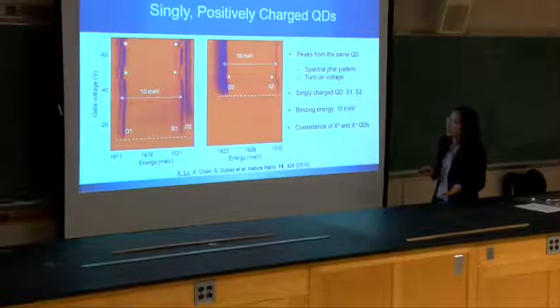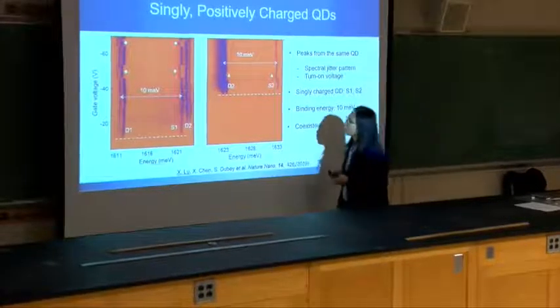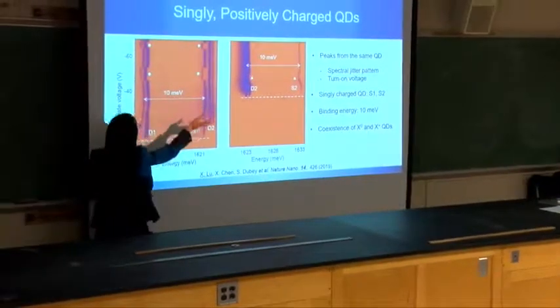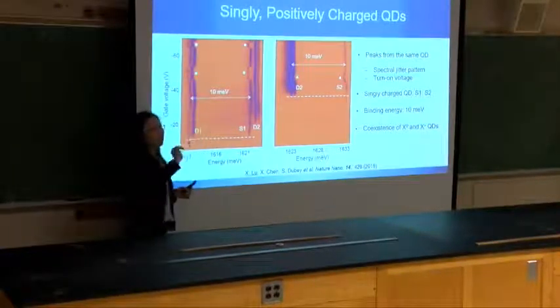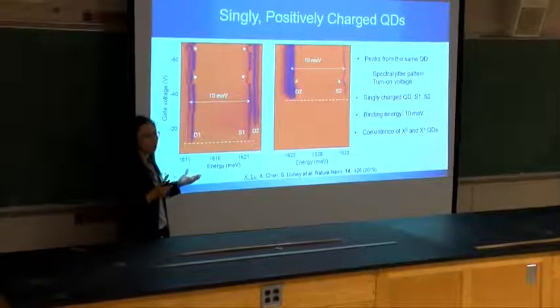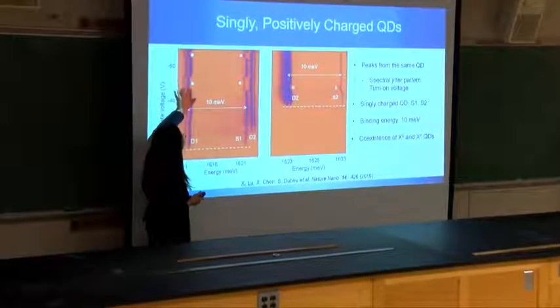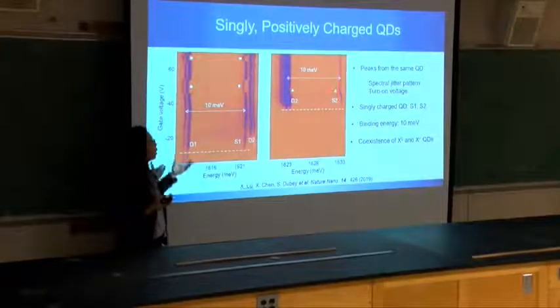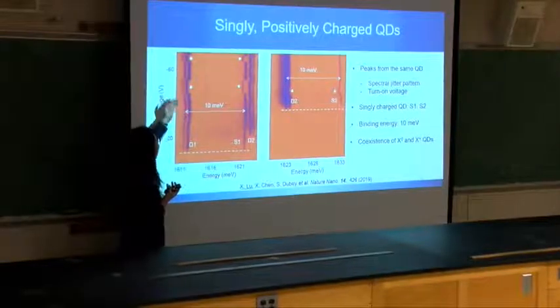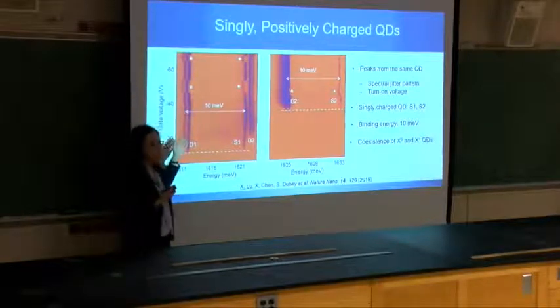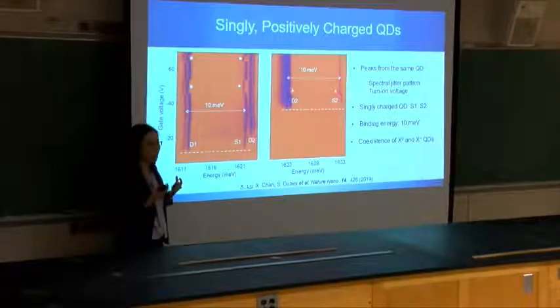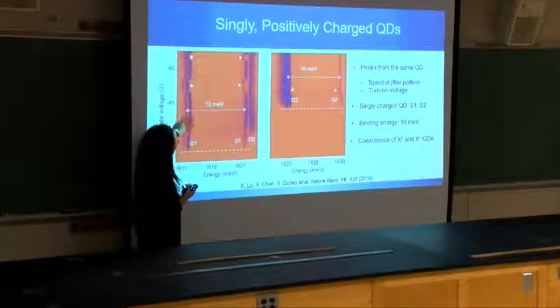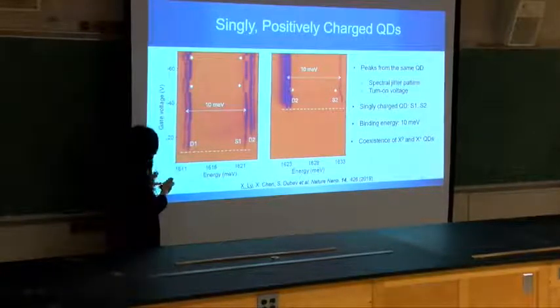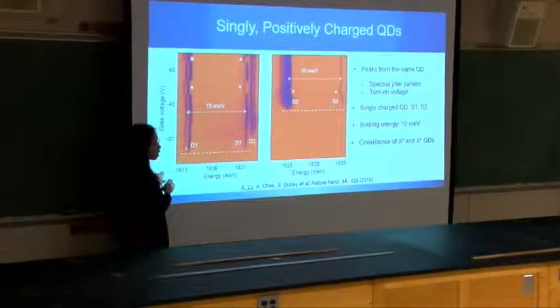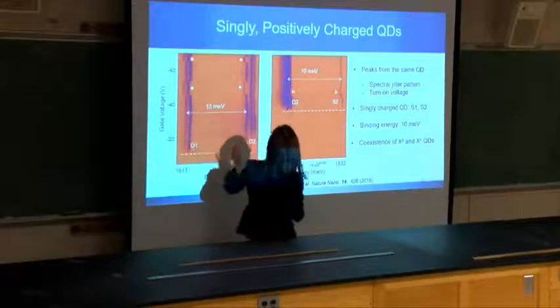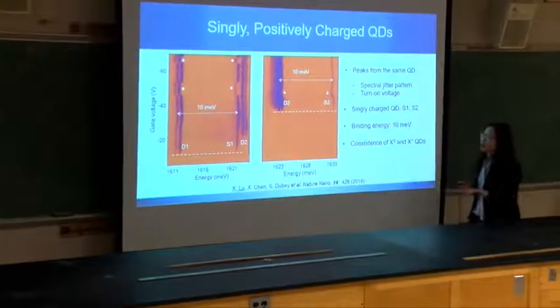Here I show two gate-dependent photoluminescence color plots. First of all, let's look at D1 and D2. We see that the two peaks wander together, or you may hear the term spectral diffusion, which is the same thing. It's a characteristic of a quantum dot or quantum emitter, as it sees the fluctuation of the environment and the energy changes. If they change in the same way, that means the local environment they see is the same. So this is an indication that these two lines are related to one potential trap. On the other hand, the energy spacing here is about 10 milli electron volts. So we assign D1 and D2 to a neutral single photon emitter.